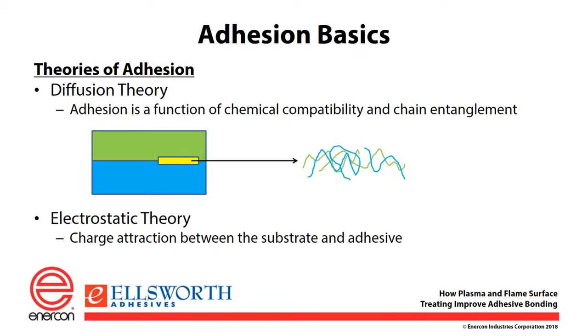The diffusion theory is a theory that's based on chain entanglement. So this would apply to plastics, for instance, where your substrate is made of polymeric chains, as is your adhesive, and the adhesive polymeric chains literally dive into the plastic substrate, and you get entanglement between the polymeric materials of the substrate and the polymeric materials of the adhesive. There are things that can be done in formulations to help with this. For instance, solvents will help bite into the substrate and allow for better chain entanglement. Fusion of plastics is sort of an example of that.